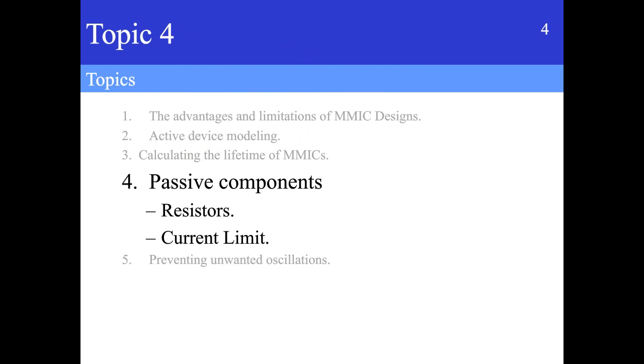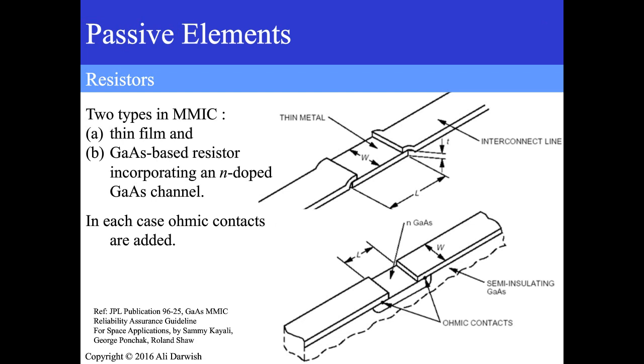Now we'll quickly talk about resistors and current limits. In the MMIC process, you usually have two types of resistors, thin film resistors and substrate resistors. So the upper one we're seeing here is a thin film resistor, and typically this is done with tantalum nitride or nichrome. And the substrate resistor is not really a physical material that you put; you just use the epi structure or the electron gas, which is built into the substrate, as a resistance value. Each one has its advantages and disadvantages.